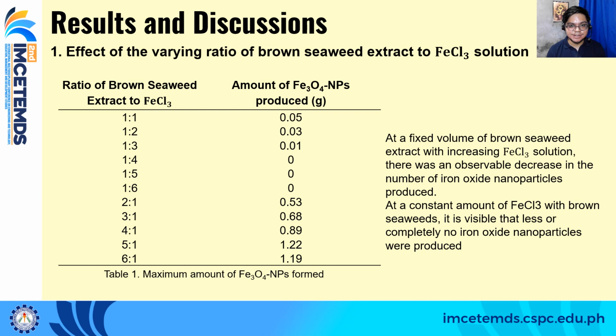Now, for the results and discussions, number one would be the effect of the varying ratio of brown seaweed extract to ferric chloride solution. From the table that is posted on your screen, we can clearly see that the maximum amount of iron oxide nanoparticles produced is at 5 to 1 ratio, which is 1.22 grams. And then at 6 to 1, the amount of iron oxide nanoparticles produced is lesser, which means that the production reaches its saturation point at 5 to 1, and beyond 5 to 1, it is expected that there would be lesser production of the iron oxide nanoparticles.